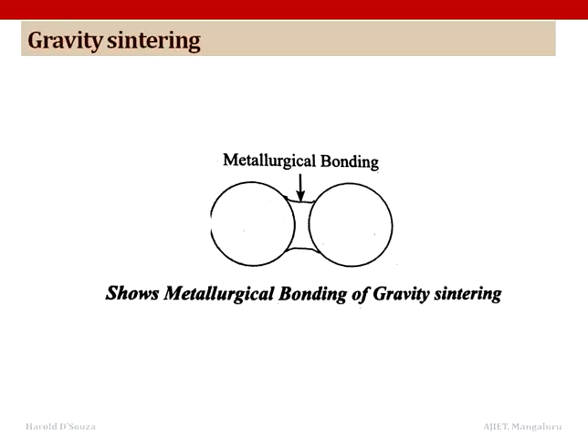Gravity sintering. Gravity or loose powder sintering is used to make porous metal parts from powders that diffusion bond easily, where most of the production parts are generally made from bronze. Now, in this process, no outside pressure is applied to shape the part. The appropriate material graded for size is poured into a mold cavity, which is void in the shape of the finished part. Now, these metal particles are then heated to their sintering temperature, at which point a metallurgical bonding takes place and joining necks are formed at the contact points.